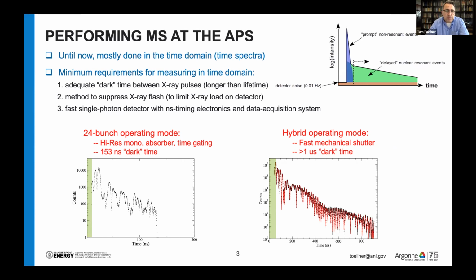So the two ways we currently do it, or have up until now done it at sector 3, one is in 24 bunch mode. We use a high resolution monochromator. This is by bandwidth reduction. We reduce the intensity of the X-ray flash, and then time gate out the prompt flash, as well as introduce an absorber to get additional suppression as needed. With this 153 nanosecond dark time available in 24 bunch mode, we end up with a time window that's about